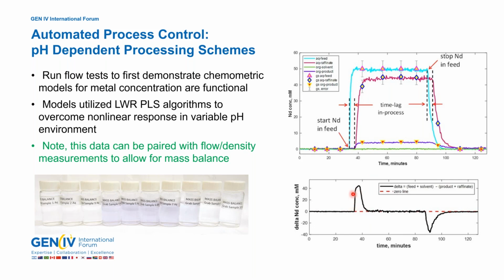What went in, we're measuring it going in, but we're not measuring it coming out yet. When we get to the point that we're in steady state out here in the middle of the process, then what we're measuring going in is equal to what is coming out, and we have a mass balance of 0. When we stop putting neodymium in the feed, we again see this deflection, a negative deflection this time, because we don't have any going into the inlet, but we still see it coming out. And then at the end, when everything is flushed out of the system, we get to mass balance again. So we are able to show and demonstrate mass balance through this experiment.